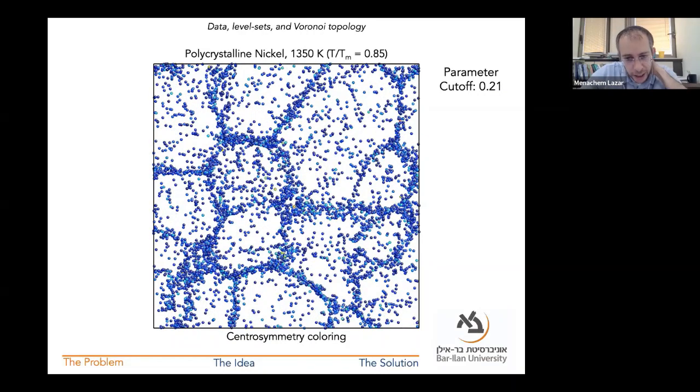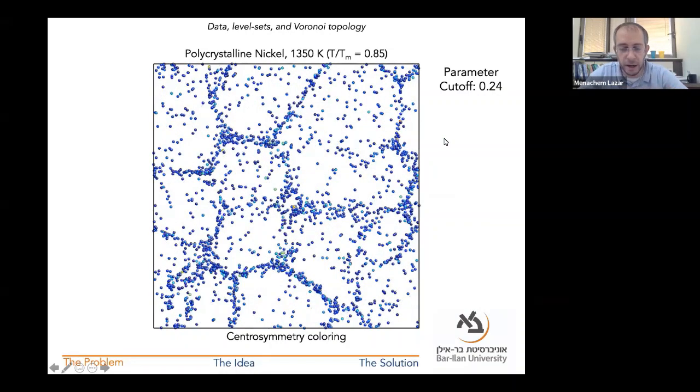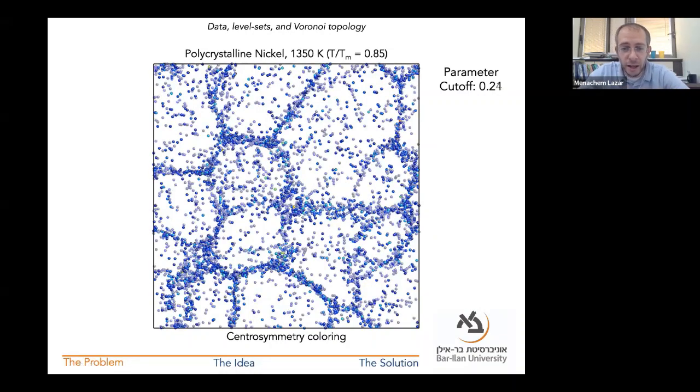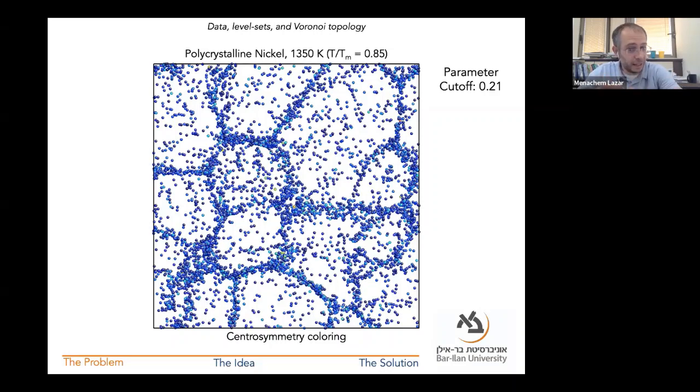Now, one thing we should notice is actually two things having to do with the error. And again, error is not precise, but one is there are certain atoms that appear in the bulk of the crystals. And if they're in the bulk of the crystals, then maybe we shouldn't have colored them. Are there actually structural defects in there? Or maybe, and this is part of what's going on in some cases, these thermal vibrations cause large deviations in these order parameter values.